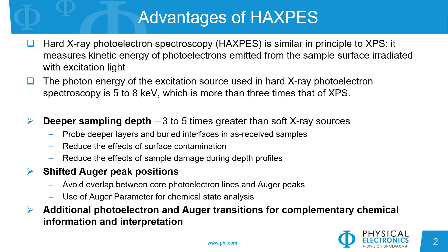Next, we can use HAXPES to shift Auger peaks that might overlap with our photoelectron peaks of interest. Lastly, with HAXPES, we can analyze photoelectron and Auger transitions that are not available with a soft X-ray source, giving us more possibilities for determining chemical environments and relative depth information. We'll have some more examples later in the talk.